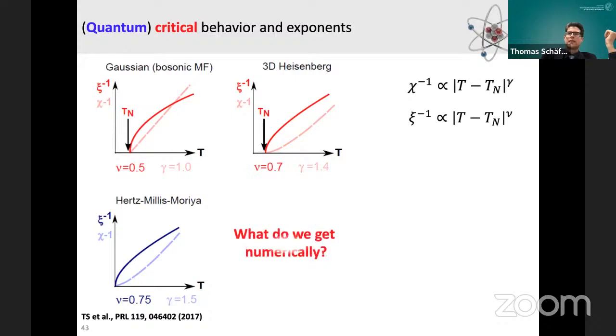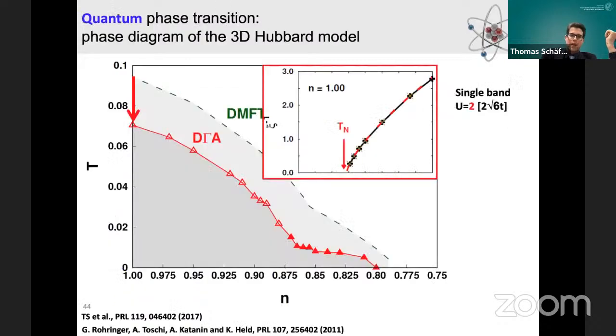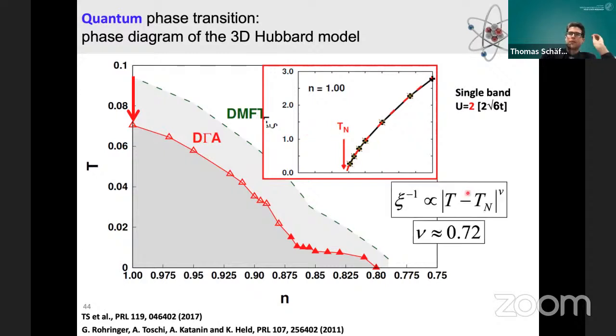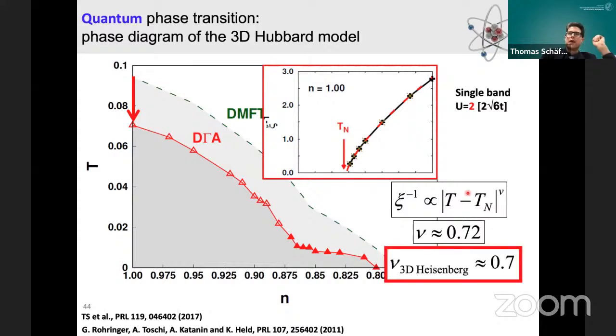So what do we now get numerically? We start again at half filling, where we have the classical phase transition, and now I plot the inverse correlation length as a function of temperature. Also, the correlation length at the phase transition diverges, so the inverse goes to 0 here, and we can extract the critical exponent. It's 0.72 in this case, which is not too far away from the 3D Heisenberg value.